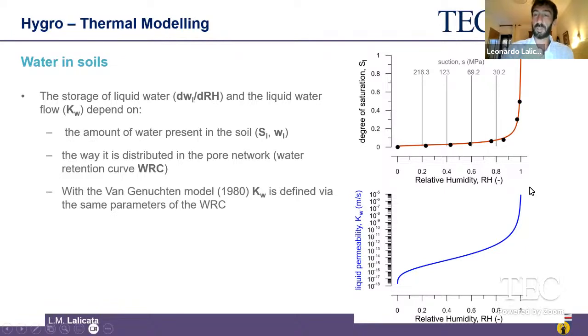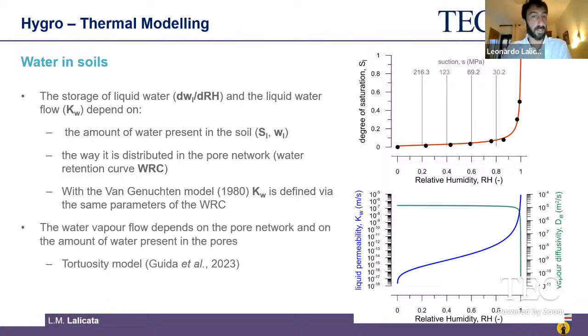But as soon as we start to desaturate our models, we get a significant drop in the liquid permeability, because some of the pores are obstructed by air and the water cannot flow through these pores. And if you want to see that the other way, what happens to the water vapor, well, it's the same thing. When the degree of saturation is very low, that means when the relative humidity is low, the vapor can easily flow through the medium, through the pore networks.